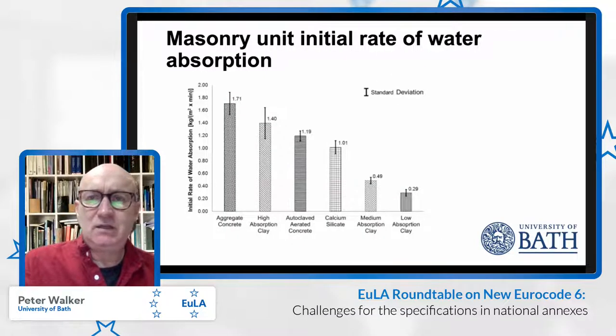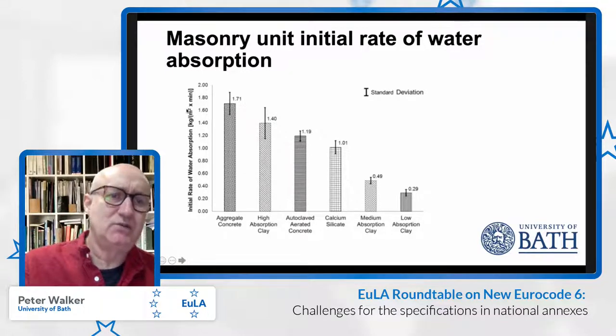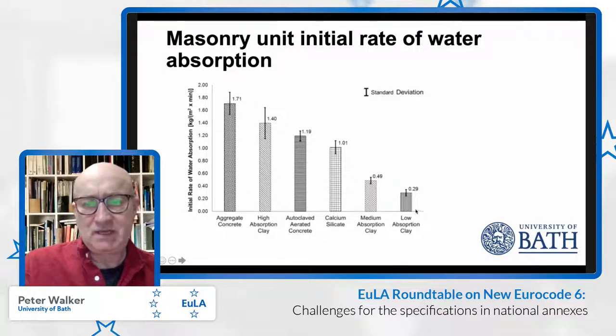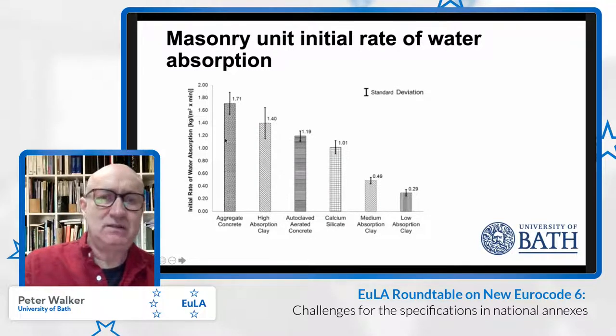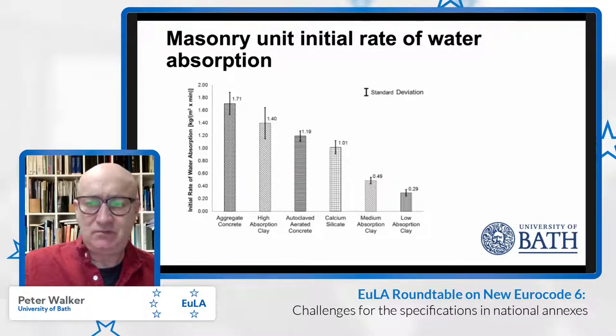And then also we looked at the characteristics of the water absorption, both the initial rate of water absorption, sometimes called the initial rate of suction, and also the total water absorption. So again, presented here, this is the initial rate of water absorption in terms of kilograms of water absorbed per unit area, per square meter per minute. And again, presented in terms of decreasing water absorption. So the concrete block had the highest initial rate of water absorption, down to the clay brick, the low absorption there. And so again, these ranges are sort of in keeping, I think, with previously reported values.